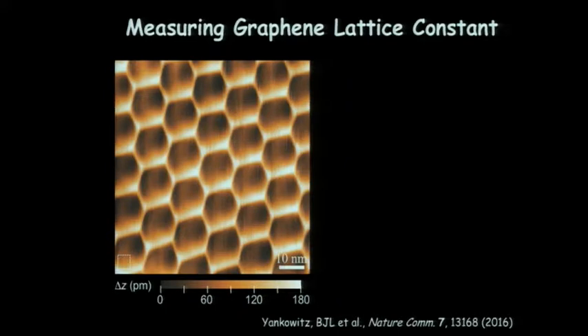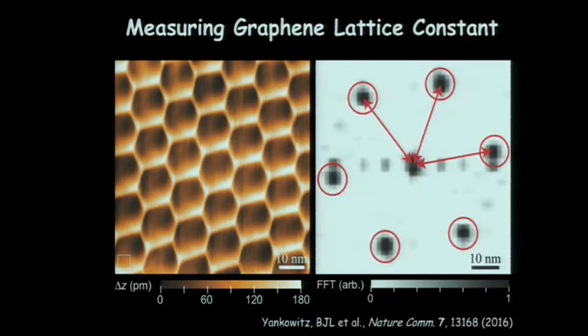So we want to go and actually measure the graphene lattice constant to be able to see if there's strain in the sample. We wanted to map out throughout this thing what the lattice constant looks like. So we take a little box here, this white box. We take a high resolution topography image there. When you do that and take a Fourier transform, you can map the lattice vectors of the graphene. So we have the lattice vectors there. We measure the length of them. That'll give us the lattice constant. And now we just take this box and we take the same measurement all over the sample. So we map the entire area.